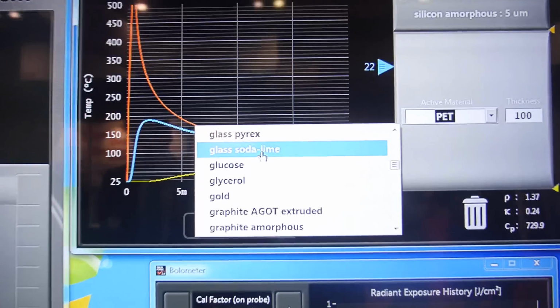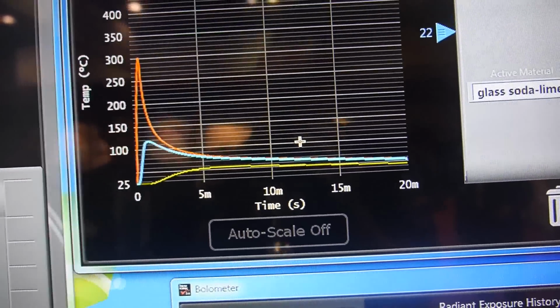Well, let's just say pick soda lime glass. And actually what you saw very quickly here was that when I use soda lime glass as a substrate, the glass is a much more conductive material, thermally conductive material than the polymer was, and so the maximum temperature you could reach was much lower, because that was allowing more heat to come out of the top layer during the course of the pulse.